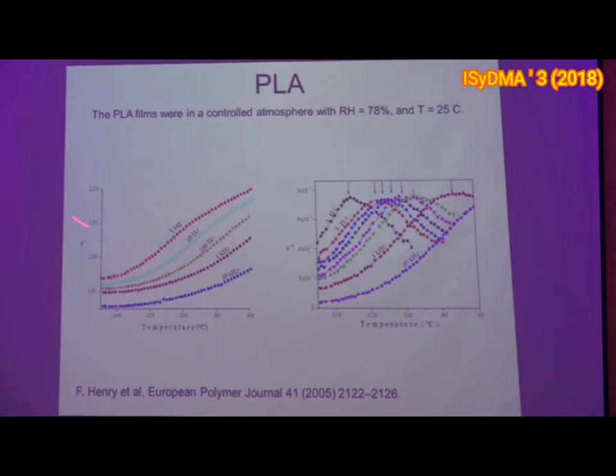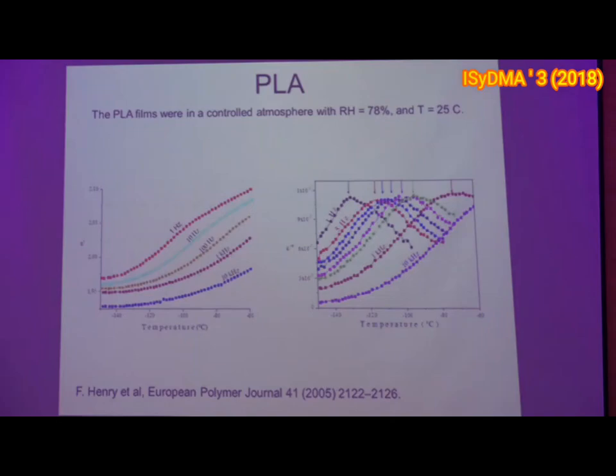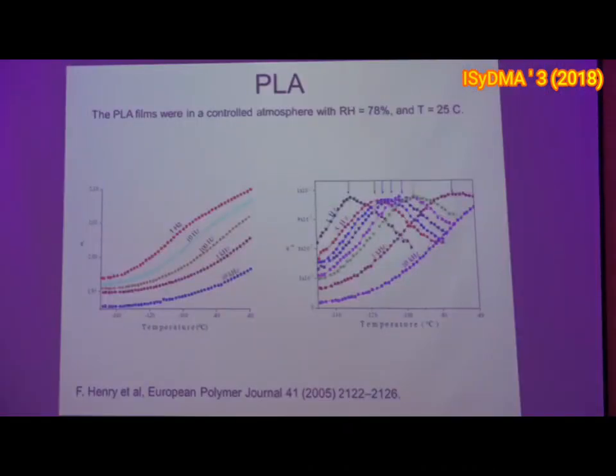In this case, we fix the frequency, and we are just seeing what happens when we change the temperature. So we use a cryostat, and we put the PLA films inside the cryostat to change the temperature. We sweep the frequency, and in this case we use this representation. That is the real part as a function of temperature, but I can do the reverse. I can fix the temperature and see what happens as a function of frequency. Well, we have the same information.